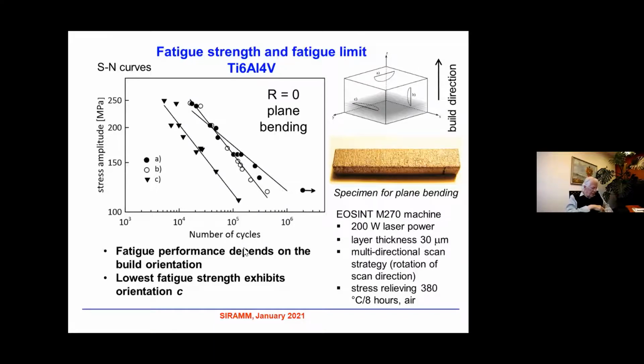Let us start with Ti-6Al-4V. We have prepared or built specimens for plane bending. You can see here an example of such specimens. The specimens were built on an EOSINT M270 machine with 200 watt laser power. Again, the layer thickness was nearly 30 microns, and the multi-directional scan strategy was chosen. It means that the scan direction rotated in the preceding layer by some angle. And finally, the material was stress relieved at 380 centigrades for 8 hours in air.